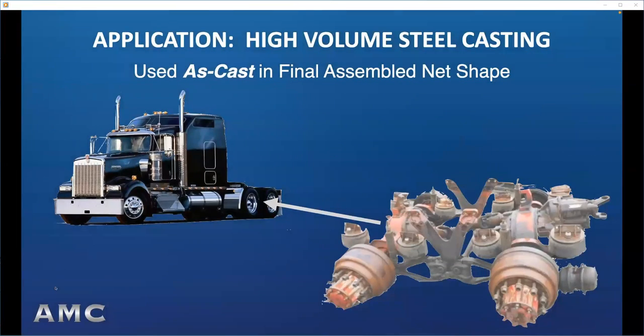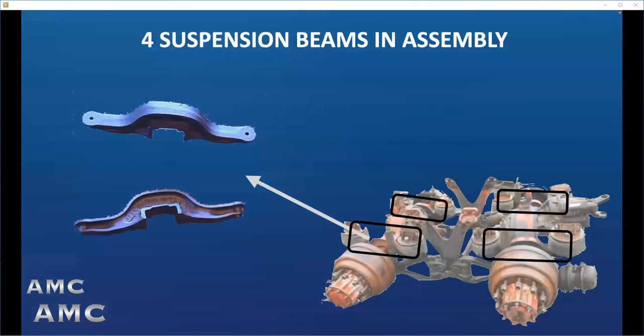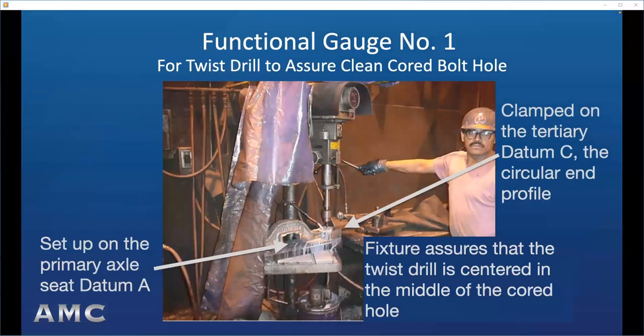Here's an example of 3 functional gauges used in assuring dimensional compliance of a steel casting used in the rear suspension of an 18-wheeler tractor. The casting is used as cast with no machined surfaces in its final assembled net shape. Shown are 2 views of the green sand casting, 4 of which are used in the suspension supporting airbags. Accurately placed and accurate cores form the assembly surfaces in the suspension.